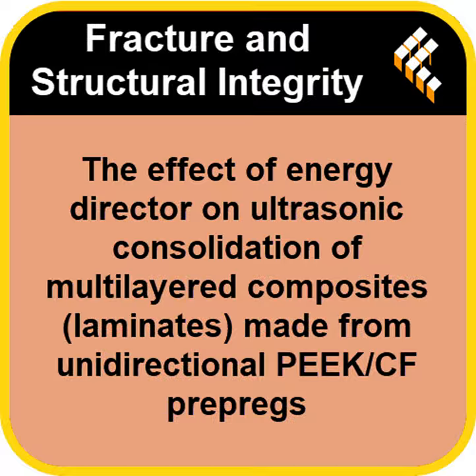Or adjusting the geometry of the energy source itself. Exactly. Decreasing the sonotrode area could lead to more uniform energy transfer into those fusion zones. That should help spread the heat more evenly and maybe even eliminate the localized damage they saw at that 1200 millisecond mark. This has been a truly fascinating deep dive into a manufacturing paradox. The key takeaway for anyone building these high-stakes components is that sometimes removing the traditional complexity actually gives you a stronger, more reliable, and faster product.